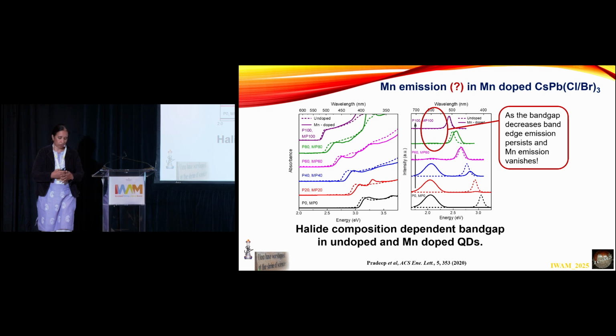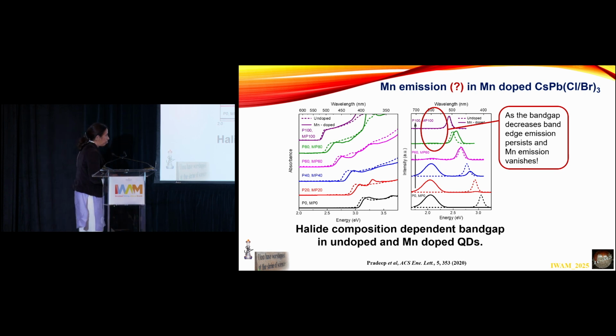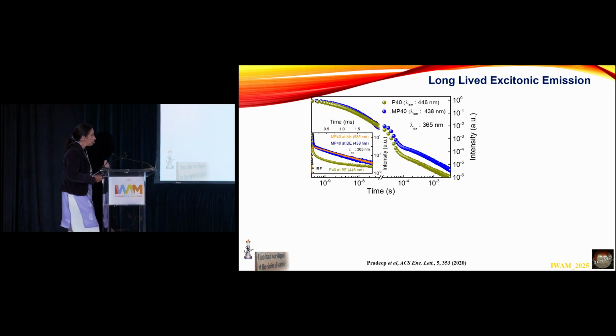It was initially thought that manganese is not effectively doped into the nanocrystals, but we have since shown that if you look at only the slow component, then manganese is indeed there, but it's not showing this signature manganese emission peak. In order to understand this, we first looked at the lifetime. When you look at the long-lived excitonic lifetime, you see that it matches very well with the manganese. So the orange one here is the manganese emission, and the blue one here has a very fast decay component followed by a very long-lived component.